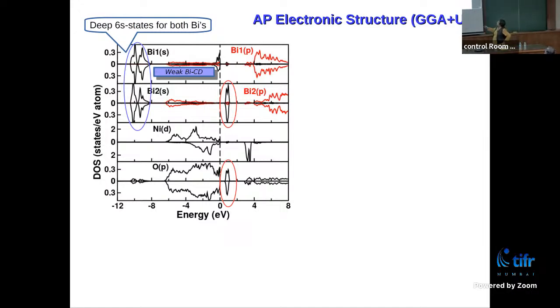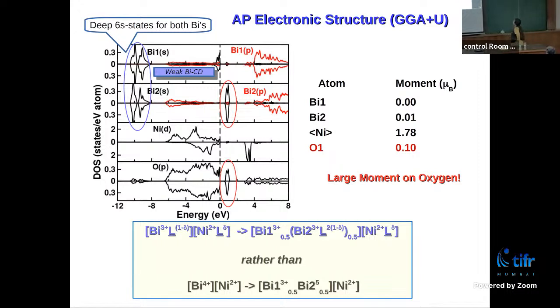This bismuth 2 instead has a split of states. The zero of the energy is at the Fermi level, and it has a split of states, which is shown here. And very interestingly, this split of states finds its partners at the oxygen. So that means the oxygen 2 minus, which should have been completely filled, is not at all filled; rather it has a split part which has its partner with bismuth 2.